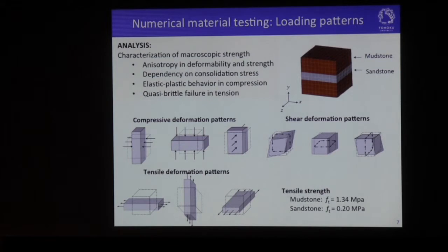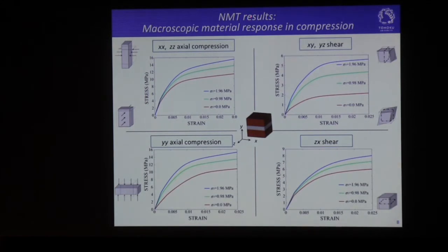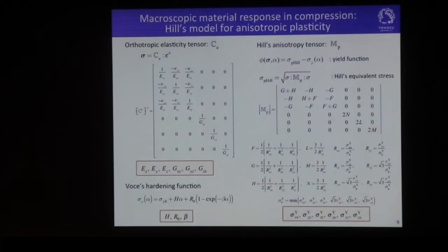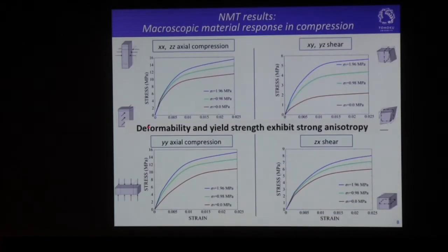Then, with this material information, we can perform the numerical material testing for this kind of microstructure composed of mudstone and sandstone. So I'd like to impose these kinds of macroscopic deformation into this unit cell to have this kind of numerical material test result. That is the macroscopic material response in compression. Okay, these are the axial response and the shear response. As you can see, the result is that the deformability and yield strength exhibit a strong anisotropy.